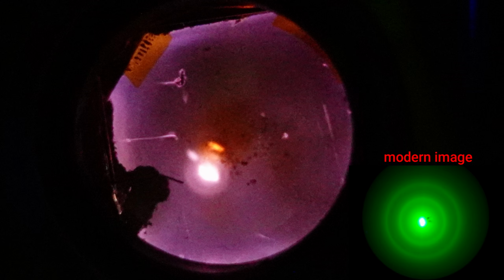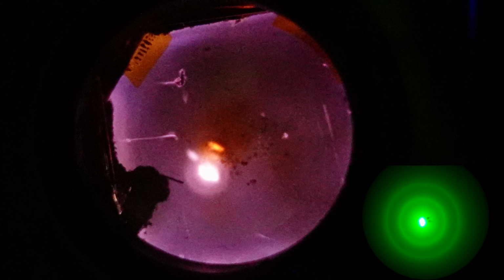Also, we can see from these two areas that the intensity of the halo increases going towards the outside of the radius, and this is what it should actually be, as the electron diffraction has a circular pattern with higher and lower intensity fringes. And we can see actually in our photo these two regions with a higher pixel light than the middle intermediate region, where we actually should predict a lower electron intensity.